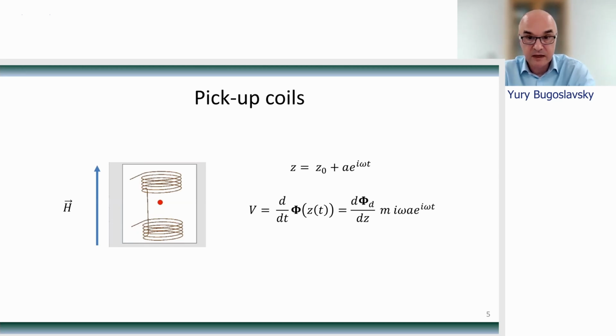ideally cancelled. In the formula you see here, the Greek letter phi denotes the magnetic flux which crosses the coil. It changes as the coordinate of the sample changes. On the right-hand side, the function phi_d is the flux produced by a unit dipole, and it describes all the geometrical parameters of the system: the size of the coil, the number of turns, the separation between the coils, and what's left is the magnetic moment m, the product of vibration frequency omega, amplitude a, and the harmonic term. So by detecting the amplitude of the voltage, we effectively measure the magnetic moment.